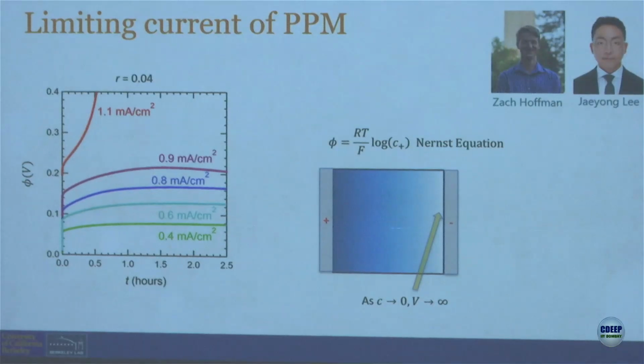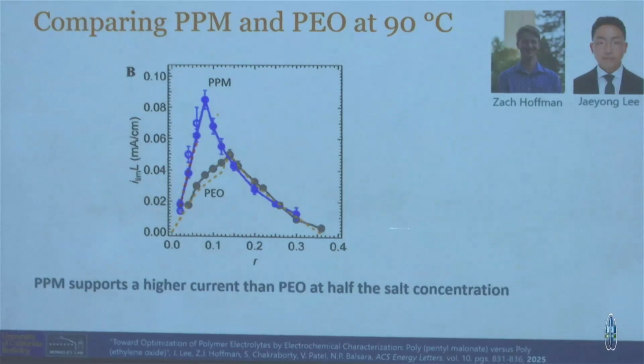And so these experiments are actually pretty tricky. And the ones that I'm going to show you were done by Zach and Jaeyong Lee. And here is this limiting current, which was 1, for the two polymers, PPM, that funny-looking polymer, and PEO, which is actually the standard, as a function of salt concentration.